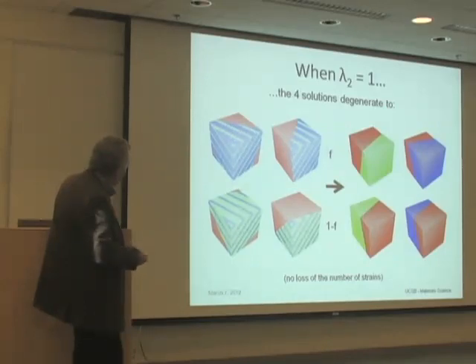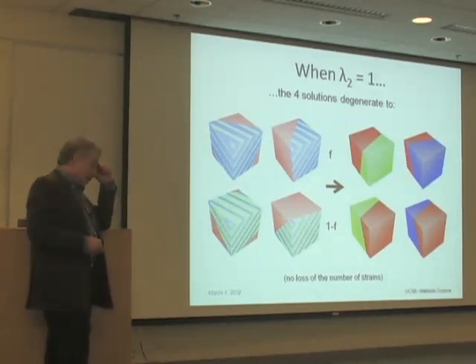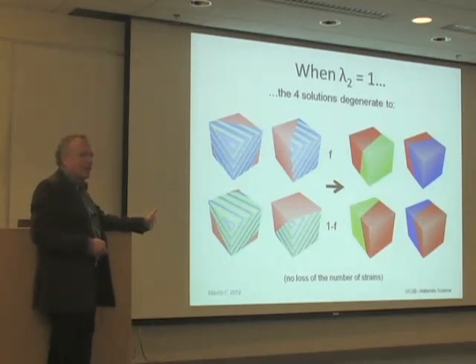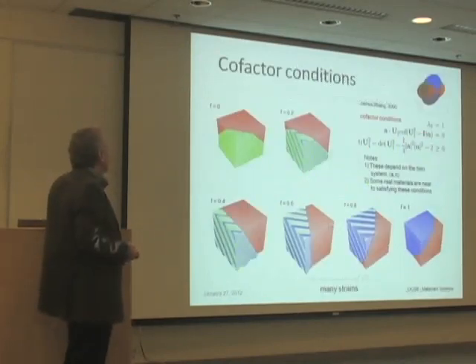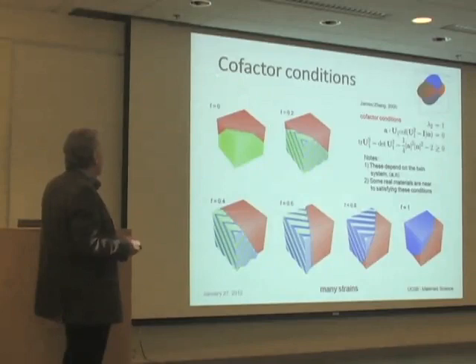So once we saw this, we began to ask the question, are there other conditions of compatibility between phases giving even better compatibility than lambda 2 equals 1? Okay? And we found a really interesting condition. We call this the cofactor conditions. So you have to satisfy lambda 2 equals 1, and then you have to satisfy some other condition, which depends on the twin system. If it's satisfied for one twin system, it's usually satisfied for many twin systems. So it can be satisfied widely in the material, let's say. And there's some inequality that seems to be always satisfied.